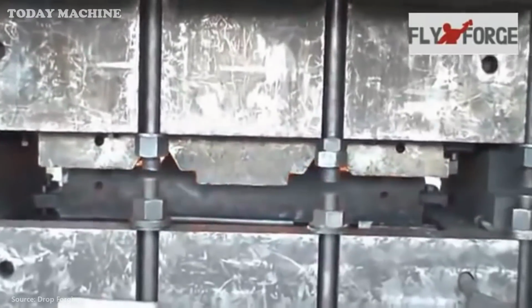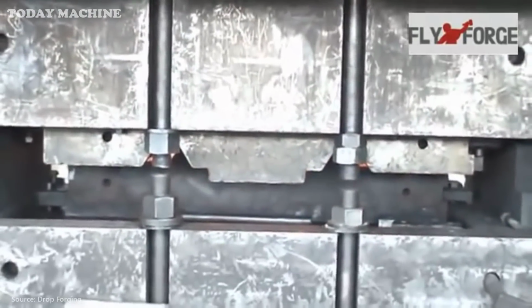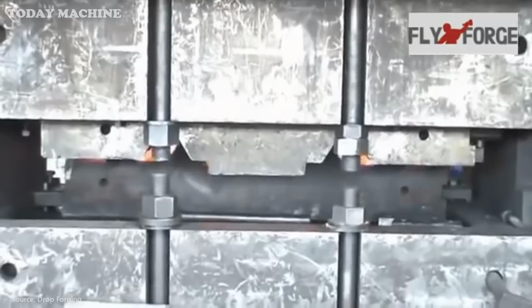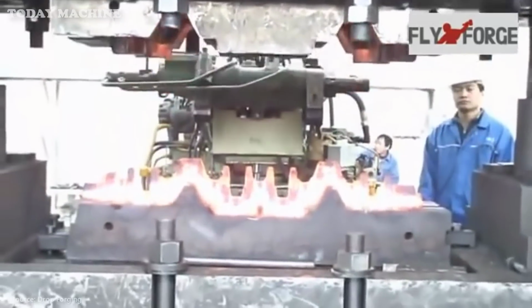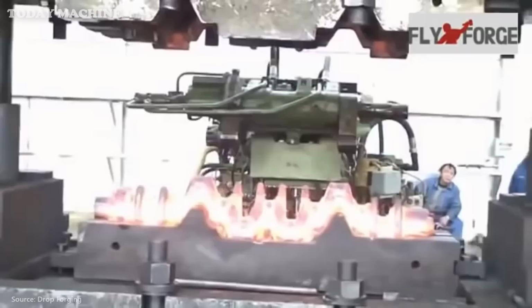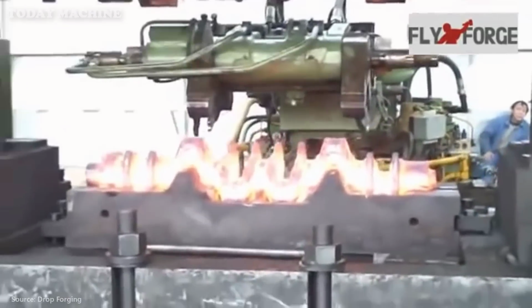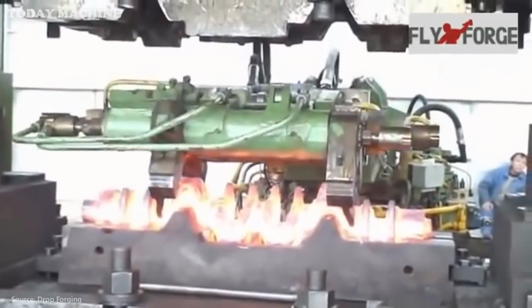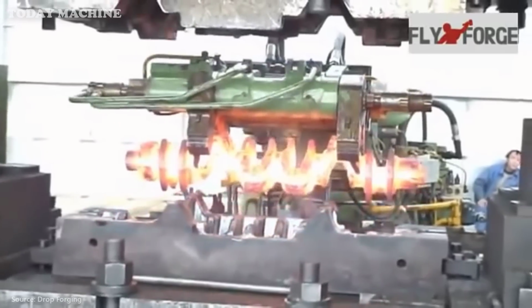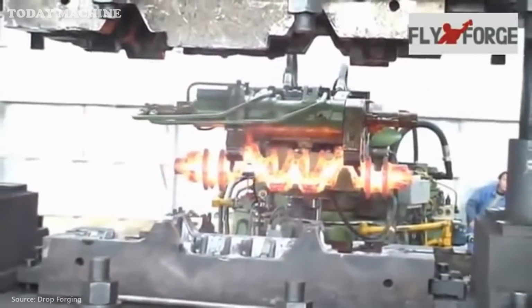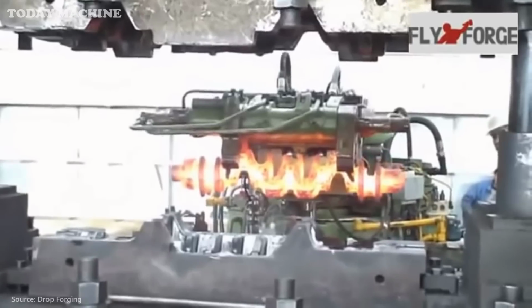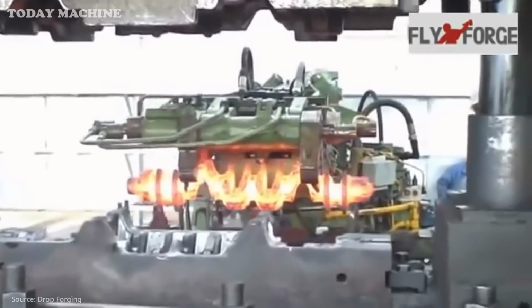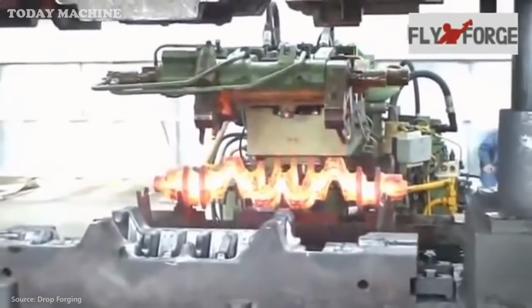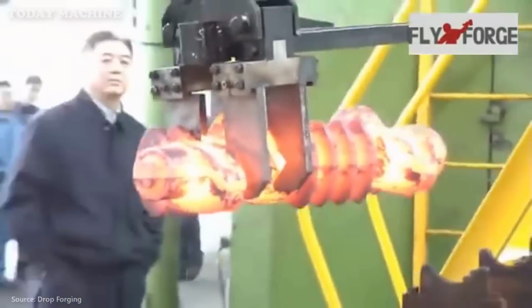After rotating the crankshaft by 90 degrees, a second correction is performed at a temperature above 800 degrees Celsius, typically 850 degrees Celsius. Normalizing and tempering the crankshaft refines the microstructure, improving mechanical properties and ensuring a hardness of HB 180 to 228 with a grain size of level 5 to 8.